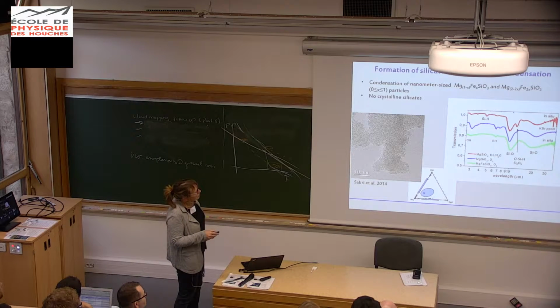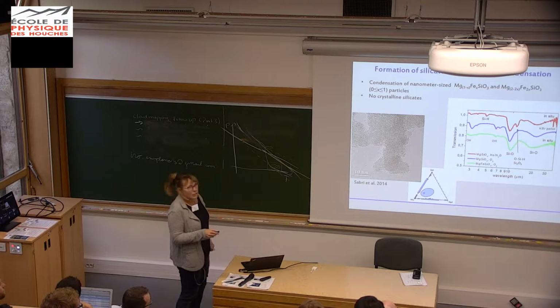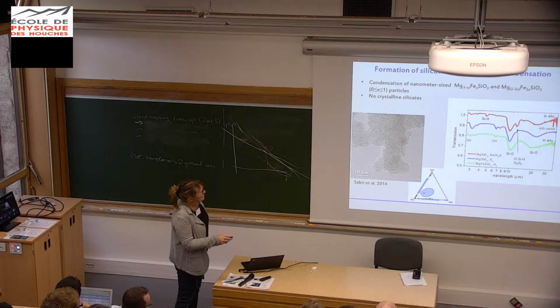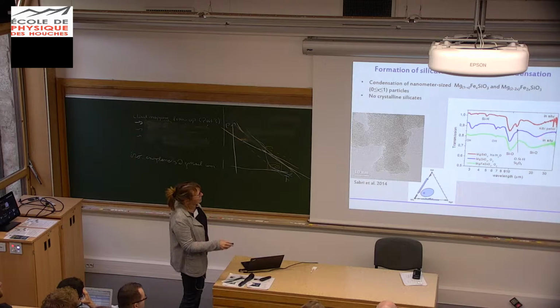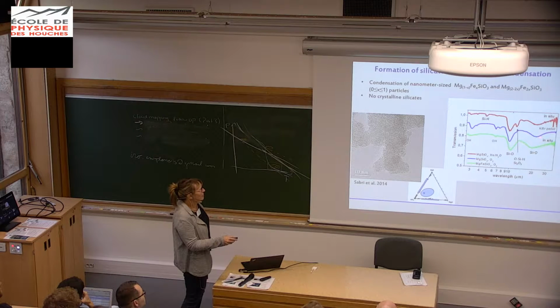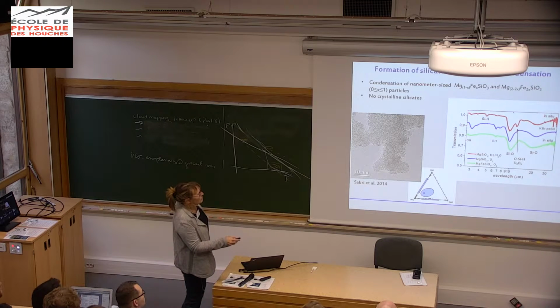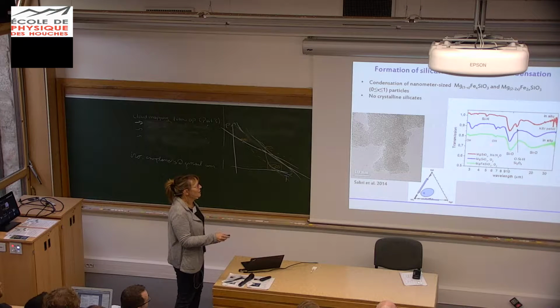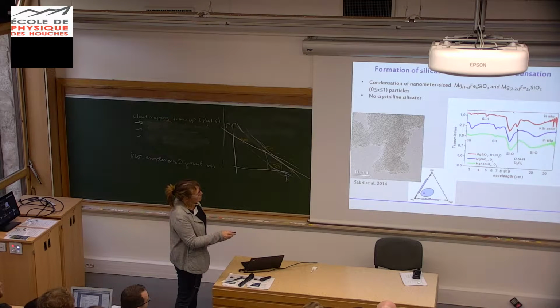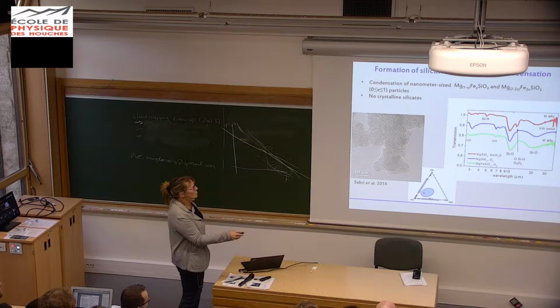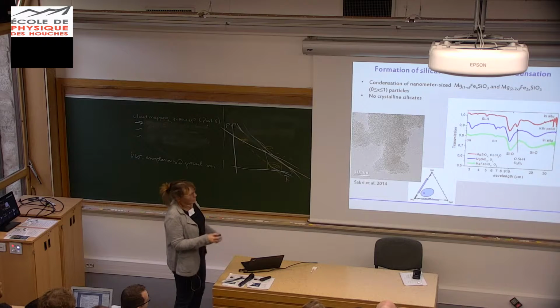So if we look at the spectral data of the condensates, you can see the typical spectral data here - this is the pyroxene, this is the olivine. The typical bands are the SiO stretching band at 10 micrometers, and the deformation or bending of SiO at around 20 micrometers. This is a little bit of water from the pellet we had to produce, so this is kind of artificial material. If you go from a magnesium silicate with a pyroxene composition to olivine, you see a shift of this band to longer wavelengths, and this other band shifts to smaller wavelengths a little bit. This is also what we would expect.